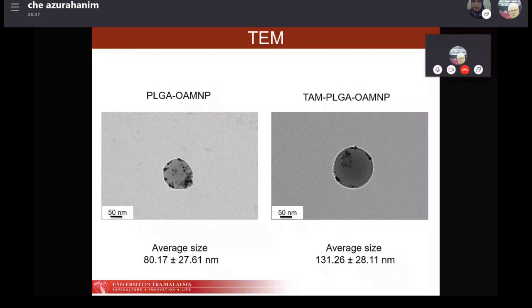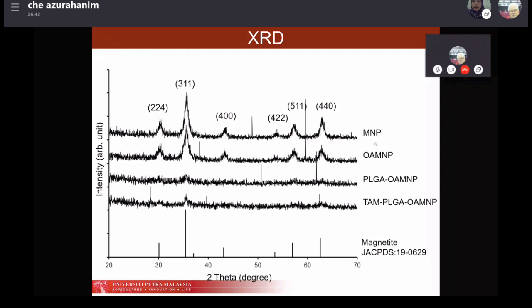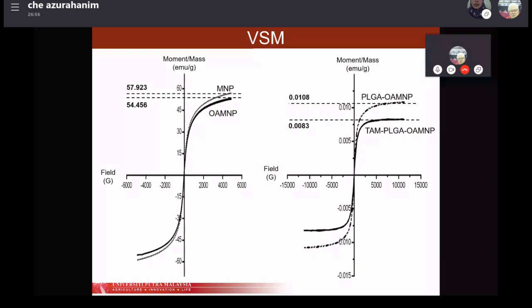So here is the XRD result, just to confirm the formation of our TAM PLGA on our oleic acid MNP. We also tested VSM, vibrating sample magnetometry. This is due to the fact that we are working with superparamagnetic nanoparticles.